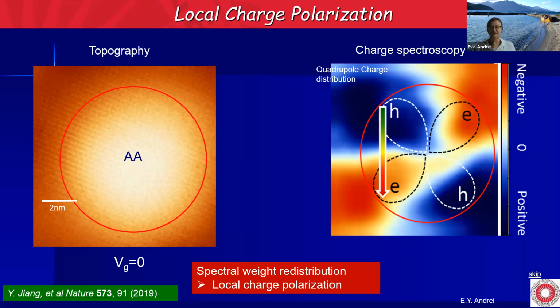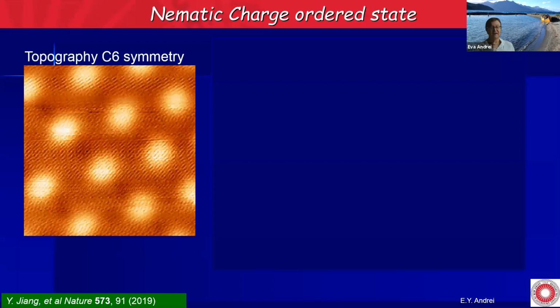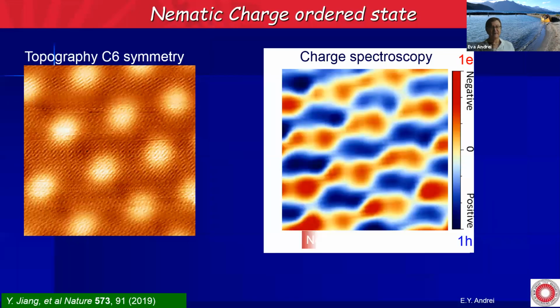And what we see here is that there is a spontaneous reorganization of the charge. Red here is negative, so it corresponds to 1 electron per moire. Blue is positive charge, 1 hole per moire, and you see that you have a quadrupolar spontaneous redistribution of the charge when we sit within the flat band. Now, if we do the same thing over a larger scale, so here you see the C6 symmetry of the sample, and if we look at the charge spectroscopy, these quadrupoles of charge rearrange themselves, so we have stripes with 1 electron per moire in red here and 1 hole per moire in blue here. So clearly this looks like we have nematic charge order.